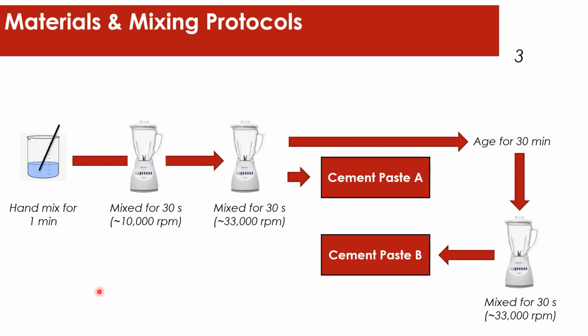Now to show how my experiment was done, I basically hand mix water and cement for a bit. I then shear it at low shear rate for 30 seconds and then at high shear rate for an additional 30 seconds. That paste is ready, and I called it cement paste A, and I print with it immediately. But as a second path, I let that paste age for 30 minutes. I shear it again and I called it cement paste B, and I immediately print with it also. So I'm trying to see if there is an effect of aging on the cement paste in terms of print quality and my ability to actually predict printability.